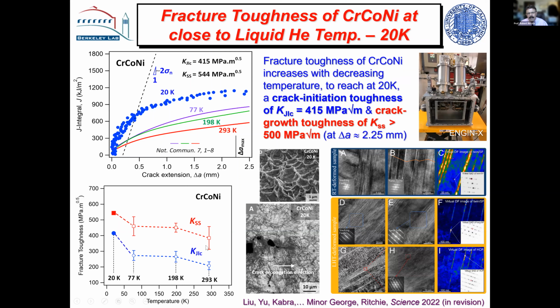You can see the same effect in the 5-component, the Cantor alloy, but not to the degree we see in the cobalt chrome nickel alloy, which is a remarkably high toughness material. So these are very, very tough materials. And this is completely intrinsic toughening generated by prolonged strain hardening from a sequence of deformation mechanisms.